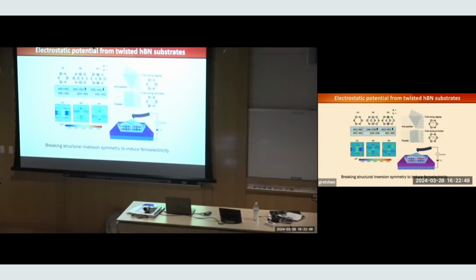We do too. One of the things that people have realized is that if you take a bulk crystal, it would have what's called an anti-parallel interface. But if you have what's called a parallel interface, you have a chance to develop spontaneous ferroelectricity in this material. And so let me just explain. So this is what's called the parallel interface.